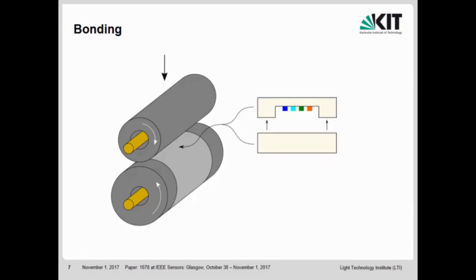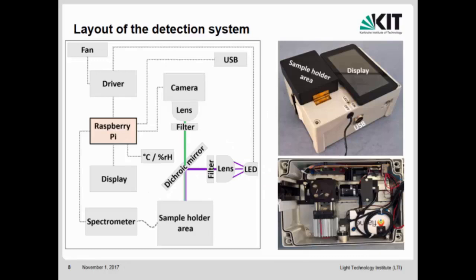And finally, the final step to manufacture our device is then a thermal bonding. We can use the same tool that we use for the imprinting in advance. Just leave out the master structure and take two sheets, the previously imprinted one with the printed structures, and the polystyrene sheet to cover it. And so we end up with the microfluidic chips at the end of the day.